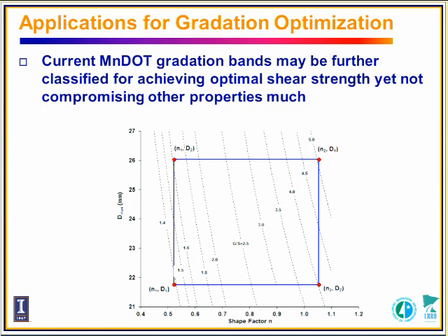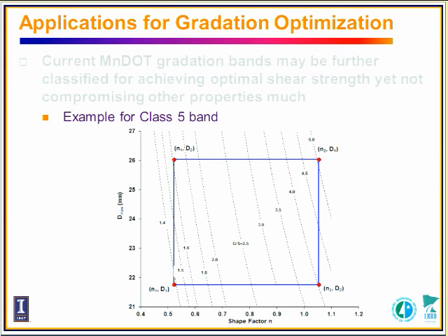Here's an application of this gradation optimization method. Here is an example of the Class 5 gradation band. Based on the upper bound and the lower bound of this gradation, we can calculate the GS value for this gradation band. Each point here represents a gradation curve, because we can fit this curve using Talbot's equation and calculate the GS ratio based on the formula we came up with. These contours represent different GS ratio values. Based on our study, 1.5 to 1.7 is the optimal range for the shear strength behavior.